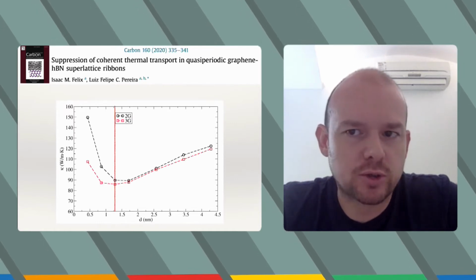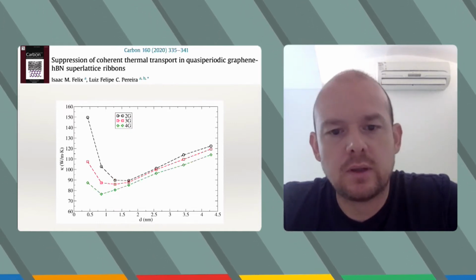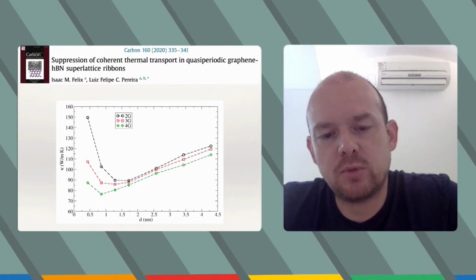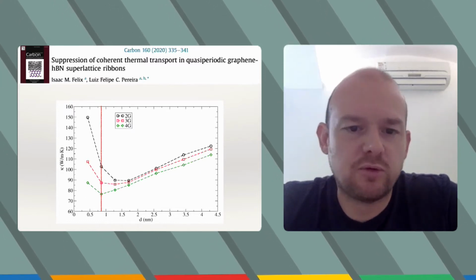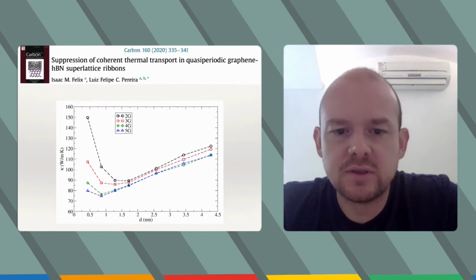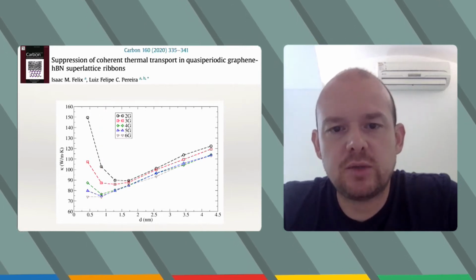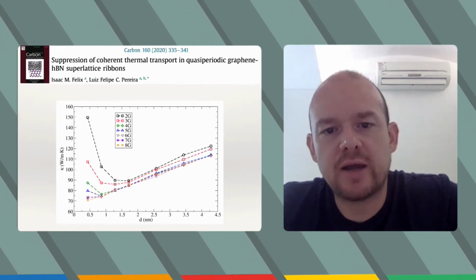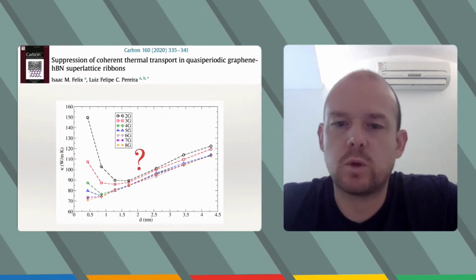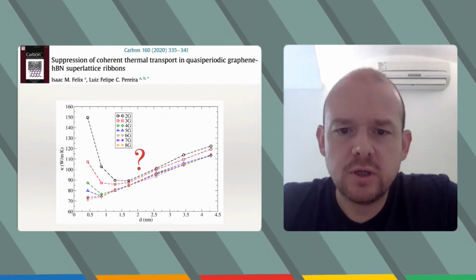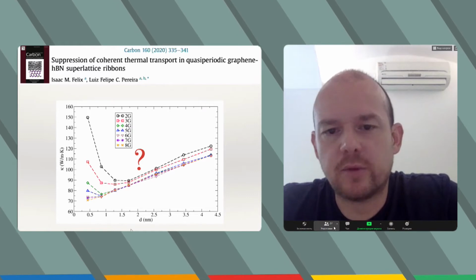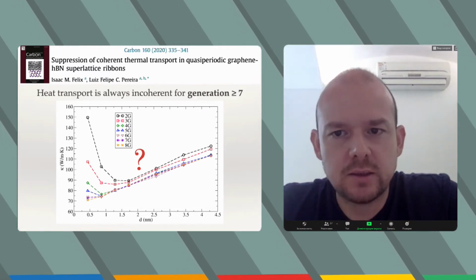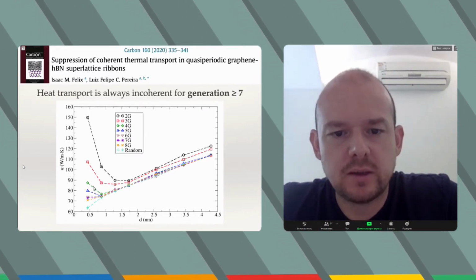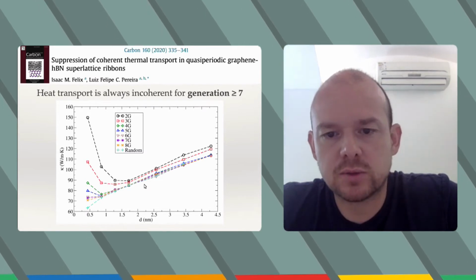It moves to a shorter domain, the minimum thermal conductivity, and then as I move to a longer domain, it moves again to the left, and it keeps moving until it eventually disappears for high enough generations. However, we are still not at a random superlattice, because I can actually compare.